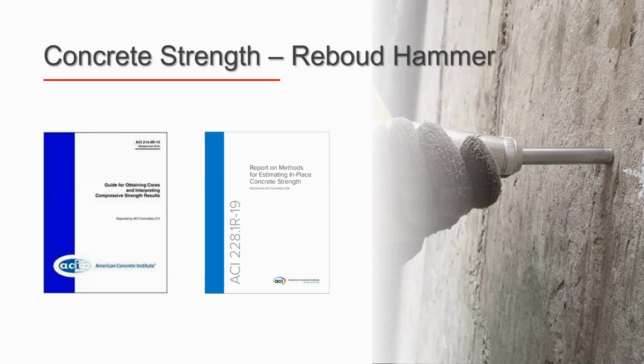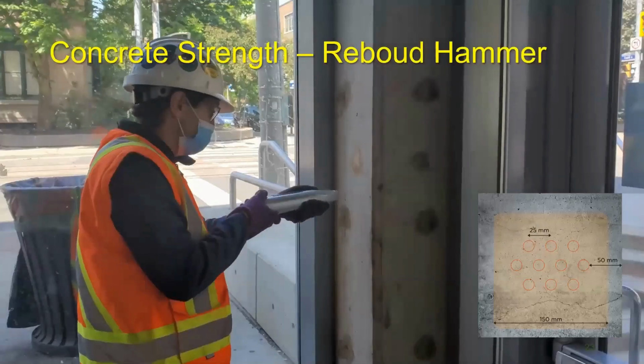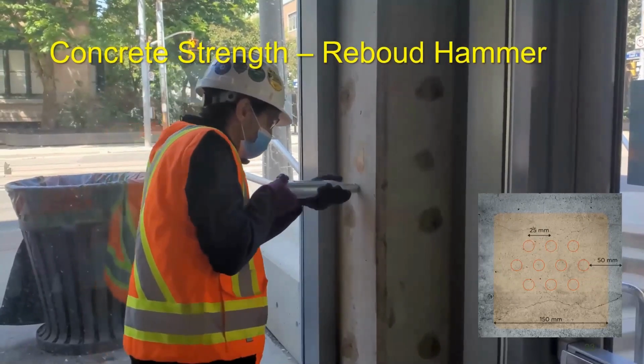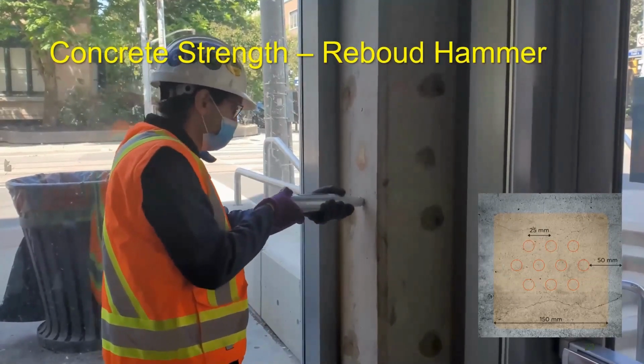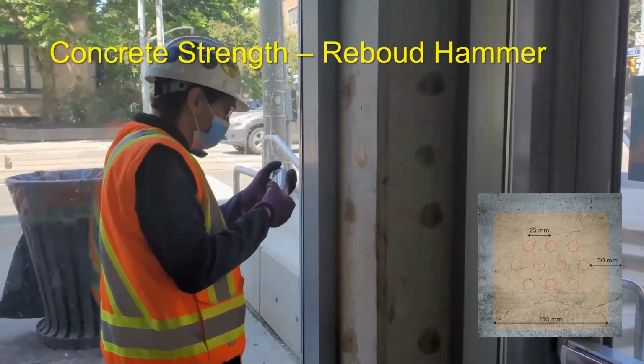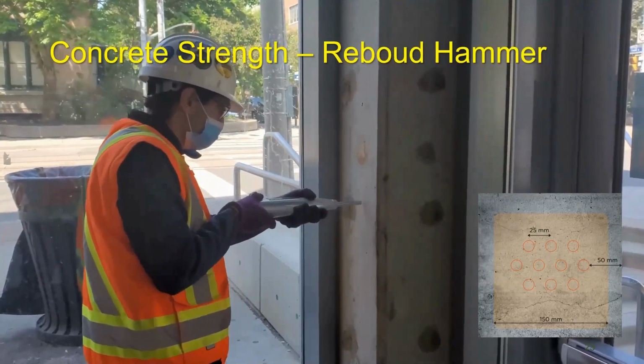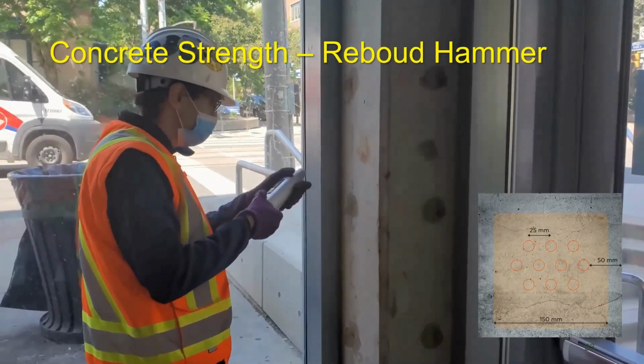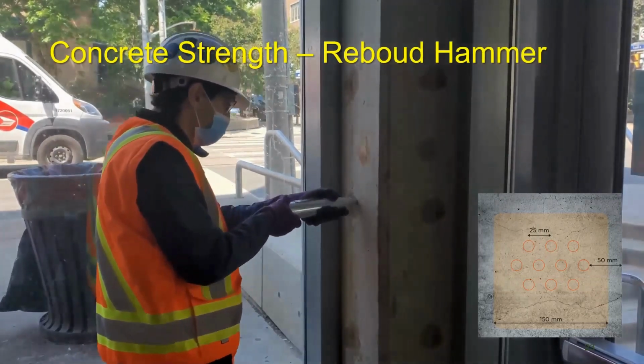important one in North America will be the ACI 228.1R committee report about in-place concrete strength, NDT for in-place concrete strength estimates. The rebound hammer is one of them. And when you combine the results of the rebound hammer with ultrasonic pulse velocity, you can enhance the estimate even further. In the next few slides, I'll show you how. The rebound hammer, as you can see in this image, is a pretty straightforward test to do. At each test point, you have to repeat the test a minimum of 10 times, and then use the average of the 10 readings to come up with the rebound number of the element.